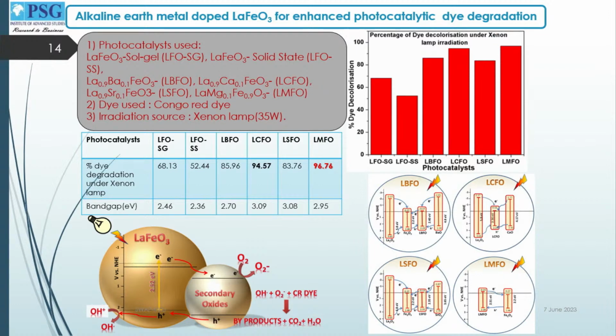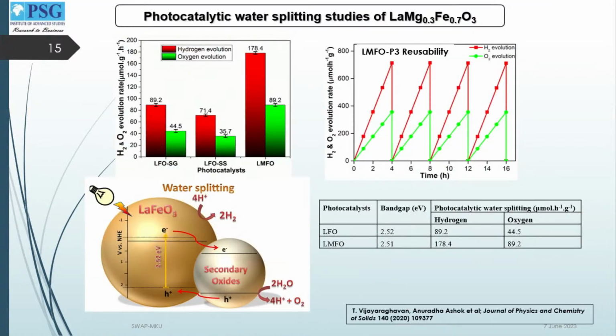Here also, when we got composite phase, we felt that we should pursue our experiments more on these multi-phase composite mixtures, because we experienced that they have a better efficiency. So we found that magnesium doped lanthanum ferrite gave better photocatalytic activity. As you can see here, magnesium doped lanthanum ferrite gave a better water splitting capability compared to the others.